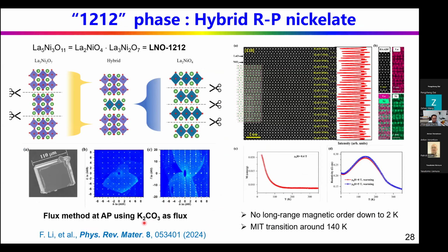Moreover, by using the flux method, Junjie Zhang from Shandong University in China can also design a hybrid nickelate, this 1-2-1-2 phase. So basically, they just combine this monolayer and the bilayer phase. They create this hybrid nickelate. This is the single crystal. It's not very big, but the quality looks okay.